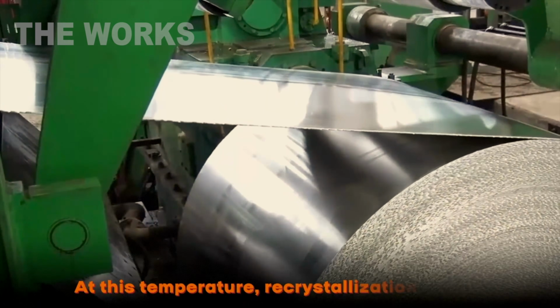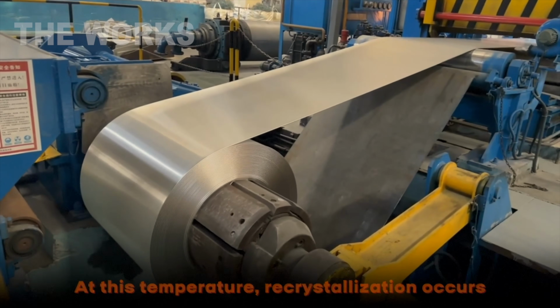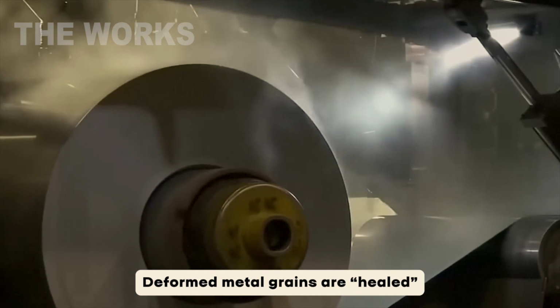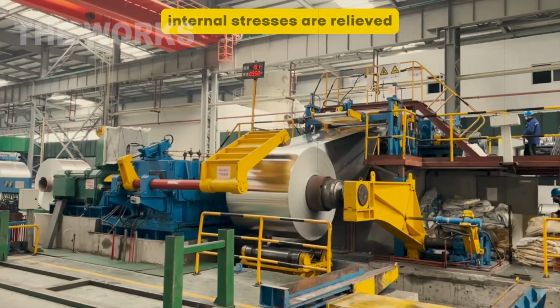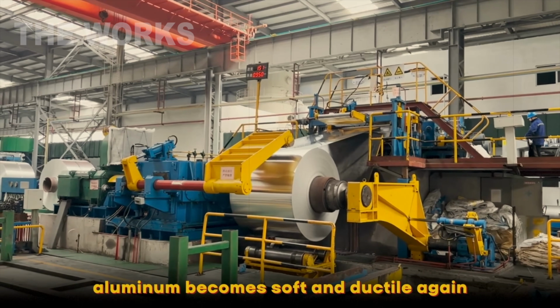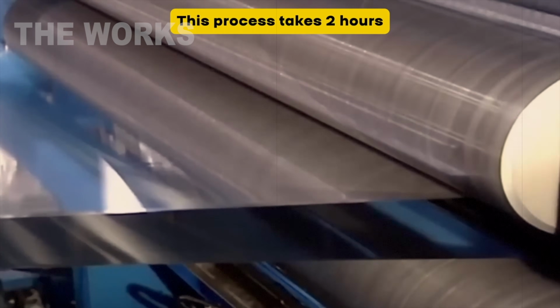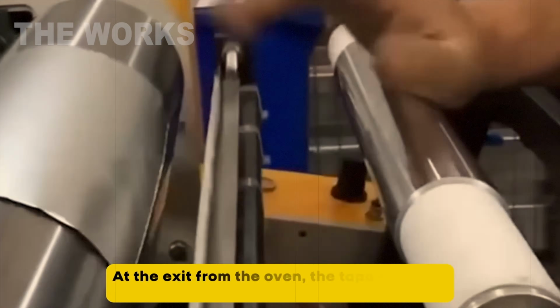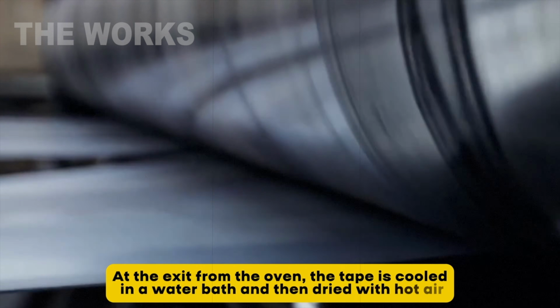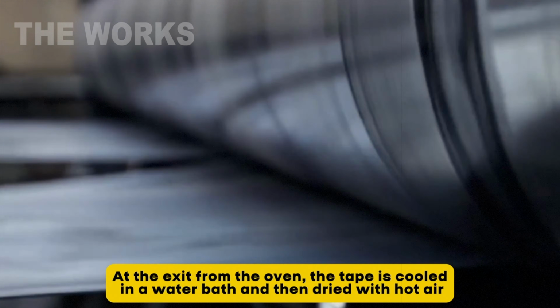At that temperature, recrystallization happens. The metal's deformed grains heal. Internal stresses release. The aluminum goes soft and ductile again. This process takes 2 hours. Coming out of the furnace, the strip cools in a water bath, then gets dried with hot air. Now it's ready for the most demanding stage, cold rolling to final thickness.